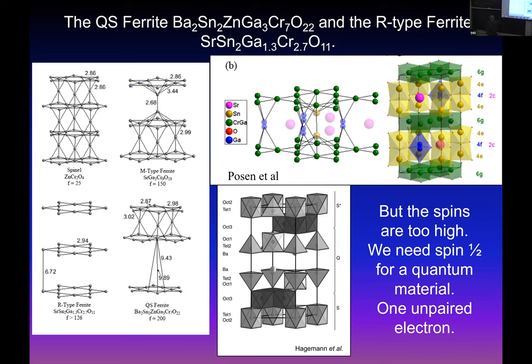Chromium is interesting because chromium is d3, which means it has no orbital preference. So chromium 3+ is typically always 3+ in a solid because that half-filled t2g orbital is extremely stable. So chromium compounds are typically chromium 3+ because they end up with three electrons, one in each of the t2g orbitals. So it's called an isotropic spin, which means that there's no spin anisotropy to favor one of those configurations over any other one. So that's particularly geometrically frustrating.